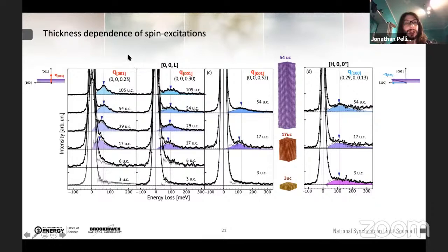So we have the intensities versus energy loss for all of the films that we measured. We covered a pretty large range, because we started from 105 unit cells and we measured RIXS spectra down to 3 unit cell films. What we observed is that at a specific momentum point, the spin excitation energy seems to be decreasing along the 00L direction. So apparently we have a softening of the spin excitations along the 00L as we decrease the thickness of our samples. Now, when we look at the H00 direction, the in-plane direction, which is not affected by the thickness, we observe very little change of the spin excitation energy.